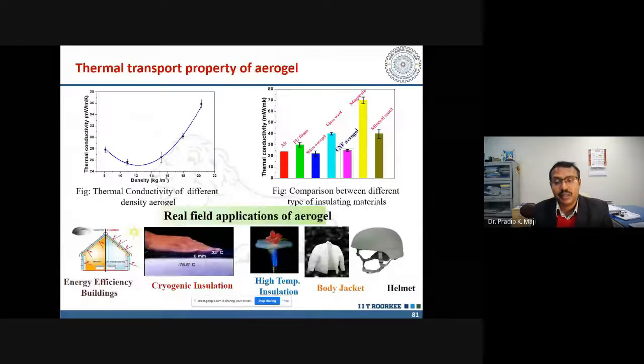And you see this is the thermal conductivity of the aerogel. Only aerogel of cellulose, we have reached up to 25.50, with 1 weight percent of cellulose fiber present in the water. After freeze drying, this water is removed, and it gives 25.5 milliwatt per meter Kelvin. Whatever we know, the thermal conductivity of air is 25 milliwatt per meter Kelvin. So we have reached to a certain level.